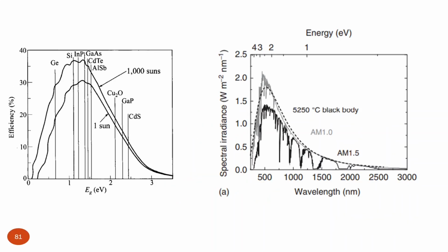Now, discussion about band gap. That's important because that is one of the key parameters which defines a semiconductor as suitable for solar applications. So here we have some efficiency theoretically predicted, assuming only radiative recombination losses based on detailed balance between absorption of light and radiative recombination emission.